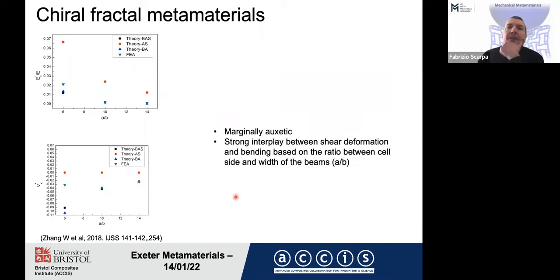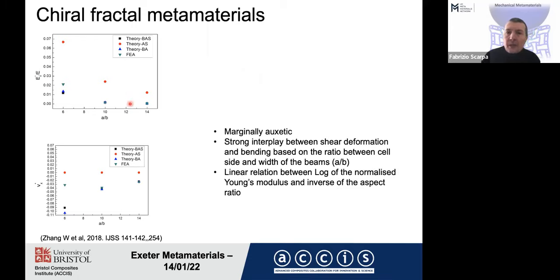The interesting bit is that in this kind of configuration you have a very strong interplay between the shear deformation of the beams making the chiral fractal and also the flexural bending of the same beams. And based on the different approaches that you take, you may obtain different mechanical characteristics. For the highest orders of the fractals, with the ratio A over B between the dimension of the beams and the whole dimension of the cells, you tend to obtain chiral fractal cells with very slender beams. So the effect given by the shear is less strong.